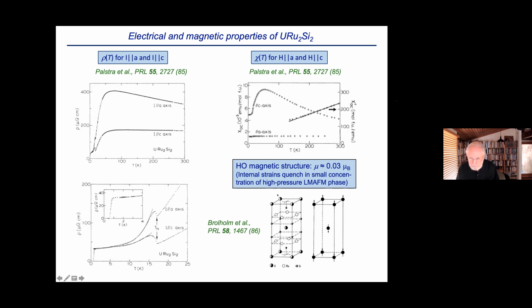And early elastic neutron scattering measurements were made. Neutron diffraction measurements were made by Collin Broholm and co-workers. What they saw was an antiferromagnetic structure shown here. However, the moment was only about a few hundredths of a Bohr magneton. And without going into a lot of details, it's widely believed that internal strains quench in a small concentration of this large moment antiferromagnetic phase, and that's really what is ordering here. And the hidden order phase doesn't appear to have any magnetism associated with it.